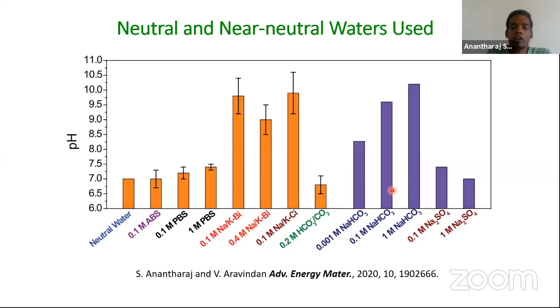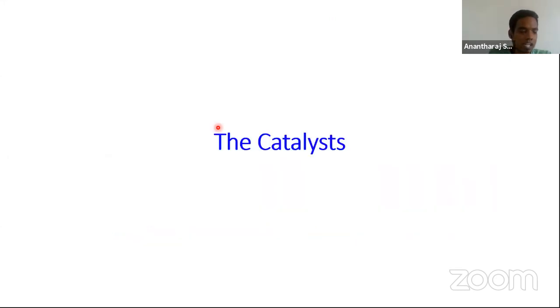All these factors will affect the choice of electrolyte, and this is a collection of electrolytes, and you can see neutral water's pH is around 7, and we have several solutions which can have pHs closer to 7 and even below 7, and we also have slightly moderately alkaline solutions which are also considered to be near neutral waters for enabling this catalyst to be applicable in solar to fuel conversion devices. So these are the available electrolytes, and you can go for any of them depending on the eventual use of your electrocatalyst. These are the electrolytes that we have encountered in literature so far for neutral and near neutral water electrolysis. So now we'll move on to the catalyst.